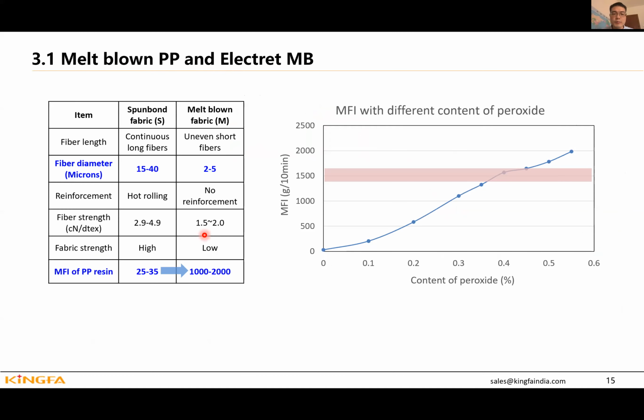And this meltblown PP, we want to find 1500 MFI, so normally the PP MFI is around 30. Some higher MFI is 100 for injection. But for meltblown, we need to find higher. So how do we increase the MFI from 30 to 1500? This is one point we should find the solution for.